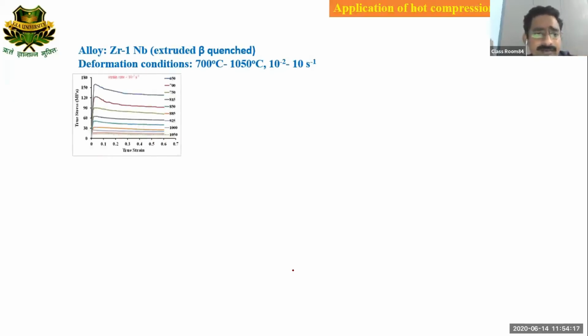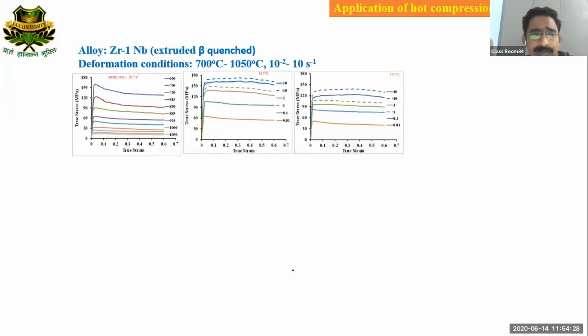So here you can see one picture. It is a true strain diagram at a strain rate of 10 to power minus 2 for different temperatures. The left side figure is at constant strain rate, 10 to power minus 2, and the right side middle picture is at constant temperature for various strain rates. These dotted lines are also the values of flow stress data, but adiabatically corrected.